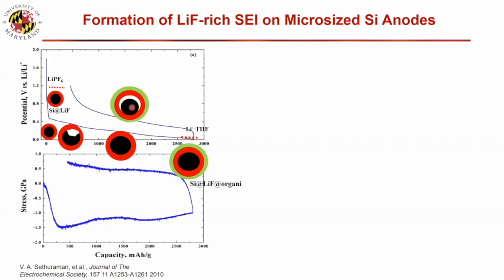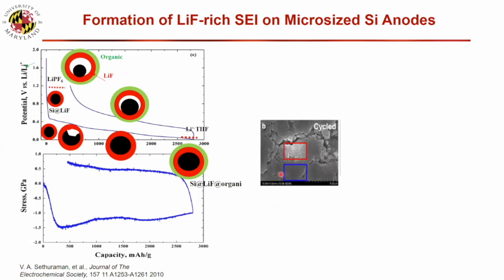So when we come back, because the bonding is so weak, the silicon will shrink, and they can easily detach from the lithium fluoride. So the SEI is stable. And then in the second cycle, they just continue the cycle. So we demonstrate this concept.